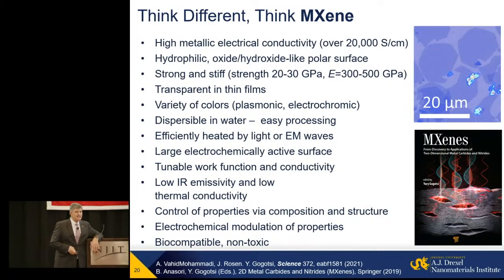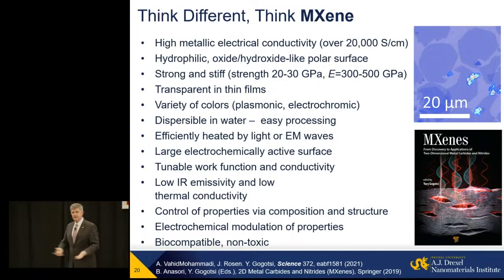So the key thing is getting properties that other materials cannot give us. And one I already mentioned to you: it's a high metallic electrical conductivity. For example, for people who don't know, if you take graphene oxide and reduce it to make reduced graphene oxide, which is widely used as a building block to make conducting films, papers, coatings, you will get, with high temperature reduction, 2,000 to 4,000 Siemens per centimeter.